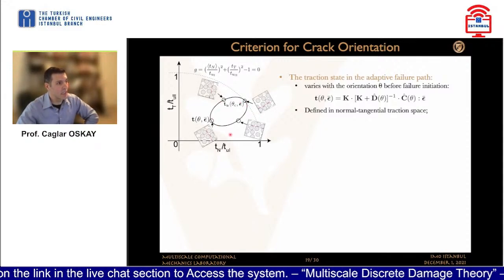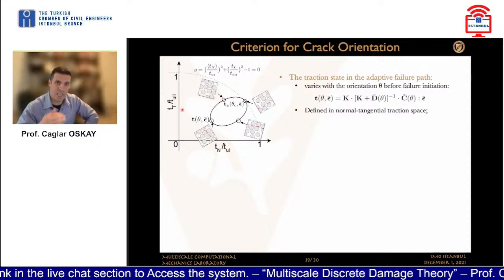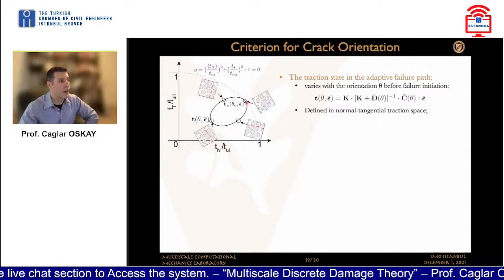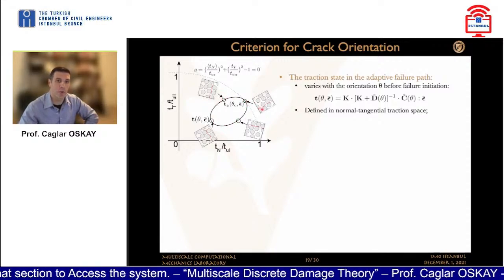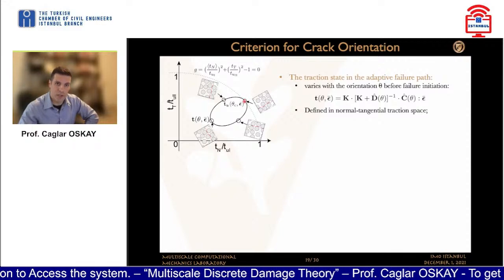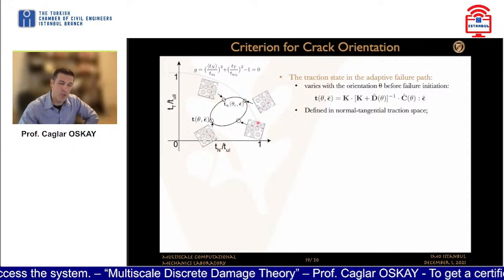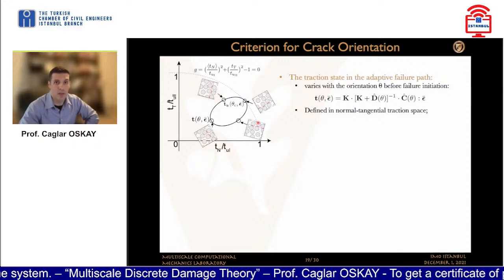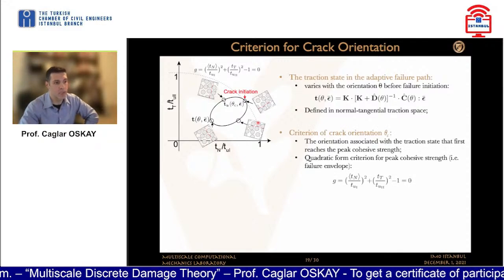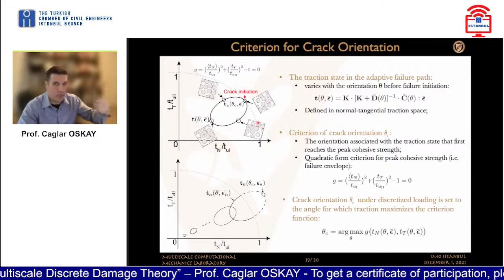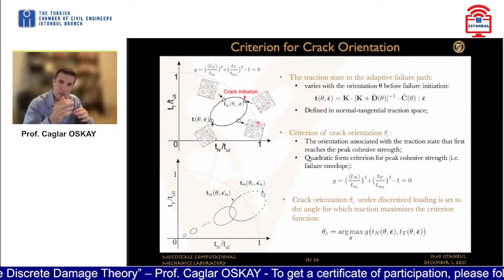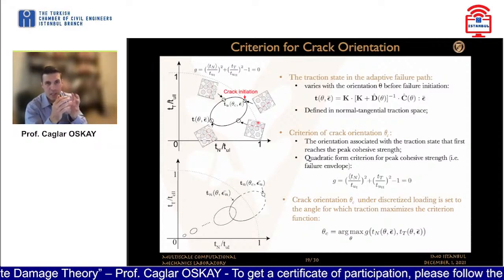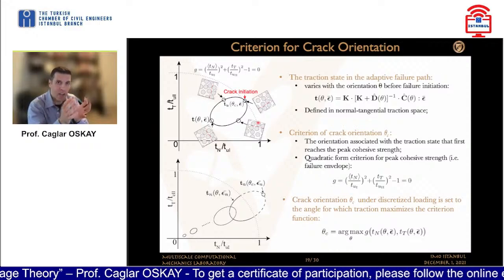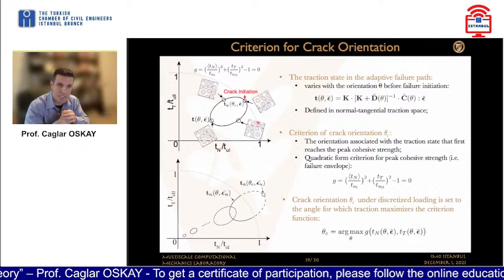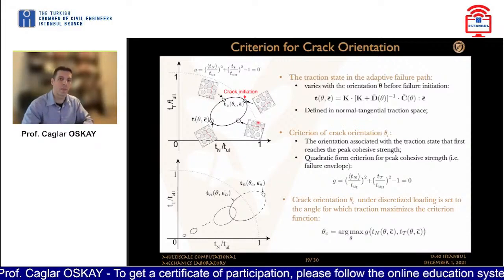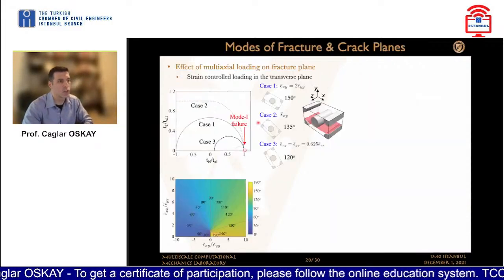And this ellipsoid here tells you the traction state on that traction separation curve, where the traction state is a function of the orientation. Naturally, the most critical one that reaches the failure criteria first is the one that will initiate, or is going to be the orientation that we essentially take. And there's also some additional work that one has to do, because you need to do this in a discrete way, and you don't always capture the contact point very accurately in a discretized system of equations. Therefore, we do a little bit more work to characterize that orientation accurately.